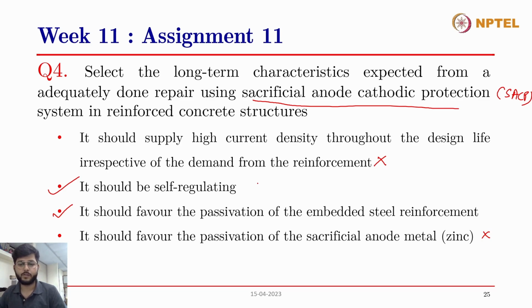Right. Thank you, Dr. Satish. Yes, the correct answer is the sacrificial anode cathodic protection systems are basically zinc-based sacrificial anode systems, which are embedded in an encapsulating mortar, a very highly alkaline cementitious mortar, which provides an alkaline environment beyond a pH of around 13, so that it allows the zinc to get corroded, and these are in connection directly with the steel rebar, so there is no external voltage applied. Rather, these sacrificial anode metal systems are self-regulating, so as per the current requirement from the steel reinforcement embedded inside the concrete, these sacrificial anode cathodic protection systems can get corroded, and they'll meet the current demand of the reinforcement with the due passage of time.